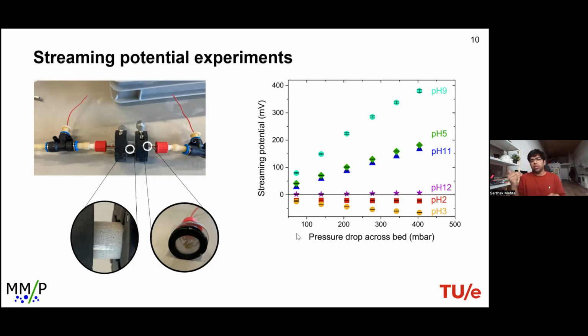So we can see that in pH 2 and 12, we see lower slopes, but we also have another question to answer. Why do we see a reversal in polarity for pH 2 and pH 3? Well, that is better answered by the silica isoelectric point.